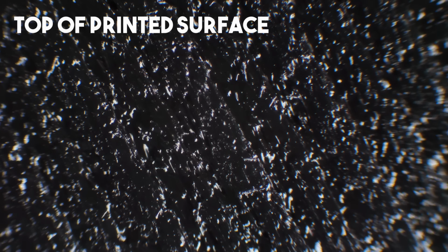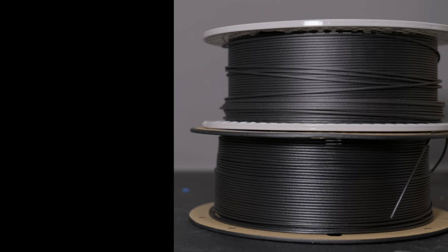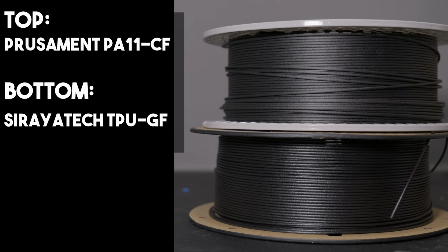Even under a microscope, we are not seeing much of the glass fibers. You might wonder why, but actually the reason is pretty interesting. The glass fibers and the polymer seem to have very similar refractive indexes, so especially with the filament being black, they just don't stand out in any way. You probably wouldn't get this surface texture without the glass fibers though, so they are still affecting extrusion in the factory, and of course the overall feel and look of the filament definitely matches a glass fiber material. You can tell it's glass fiber, you just can't see the glass, if that makes sense.